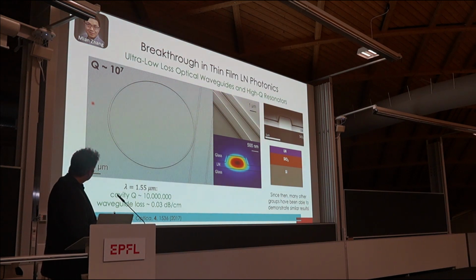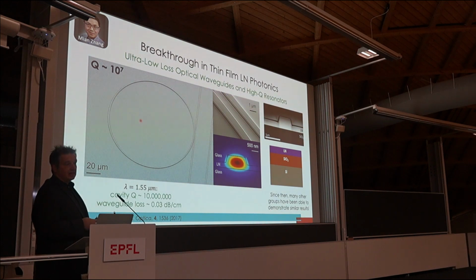What we did then, thanks to some grumpy referees who didn't believe this would properly scale, we figured out fabrication recipes to make ultra-low loss lithium niobate waveguides. At that time, we could make lithium niobate waveguides with loss of about 3 dB per meter, which is orders of magnitude better than what was done up to that point.